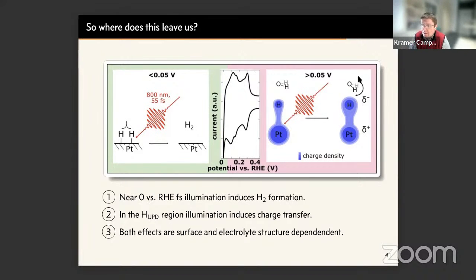Okay, so maybe two things about this. First, of course, what you're describing was what I tried to describe before, but maybe didn't describe too clearly. Yeah. So this kind of state-of-the-art photoemission experiment is one that you do with a small layer of liquid on top of the metal. Now, this will not work for perhaps all of these things. You have a mass transport problem if you actually want to produce products in this very thin layer, right? So it will be very challenging to do that kind of measurement if you're actually doing chemistry. But at least for issues of electrode polarization, because of partial charge transfer, this kind of experiment should be possible. I mean, if you have, let's say, 1.5 million to spare, Specs in Berlin will sell you a setup to do this. Then you just need the laser to add on top.